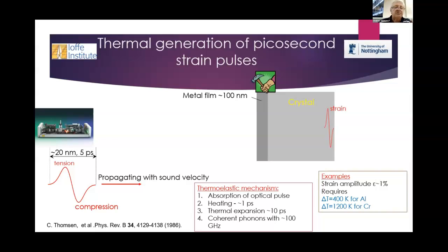In principle it's possible to generate shear waves too, though I won't discuss that here—people do this. The typical size of the pulse is tens of nanometers, and the duration is about 5 picoseconds. If we take a Fourier transform of such a pulse, we get the spectrum of coherent phonons, with a maximum between 50 and 100 gigahertz, depending on the thickness of the film and other properties of the metallic film.